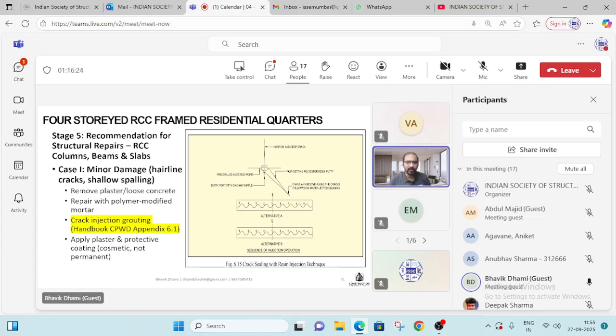So for minor repair, as I have previously mentioned in the structural repair part, the systematic approach might be to remove the plaster, do the polymer repair, do the crack injection, then apply the plaster, cover it, and provide the coating. It might be cosmetic, not a permanent but a temporary solution. The same is shown over here for the injection grout, how it looks after the pattern, and the techniques that have to be followed.